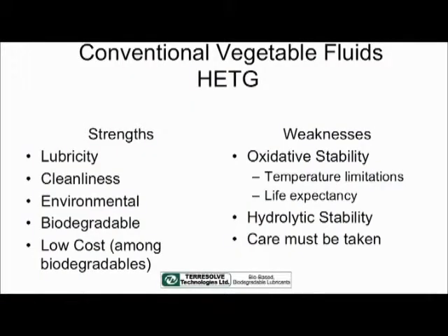Their weaknesses: you have to be very careful with their operation. All hydraulic fluids, all lubricants in general, last longer and perform better if you keep them clean and dry. More so with the vegetable oils that break down at higher temperature. If you get to 180 to 200 degrees Fahrenheit, the life expectancy of these fluids shortens dramatically.